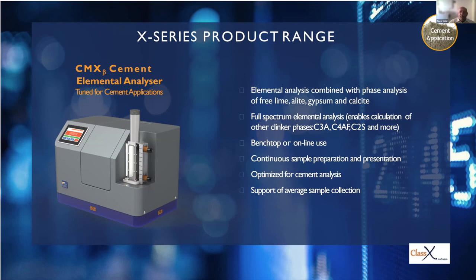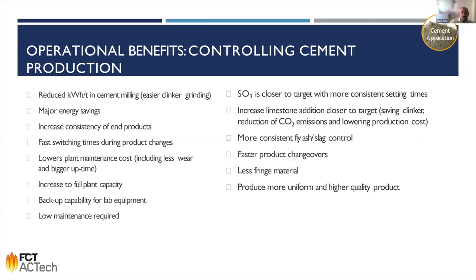And this opens for you various possibilities. On the one hand, you can reduce the clinker factor, which directly leads to a reduction of the CO2 emission. But it can also be used to add some other additions like bypass dust to the normal or expected limits so that you don't get an overshoot of the chlorine, for example. You can also use it, if you look at the process side, as this real-time instrument gives you very, very important information on when to switch between different cement grades, so that you do not waste the expensive product in the wrong silo.